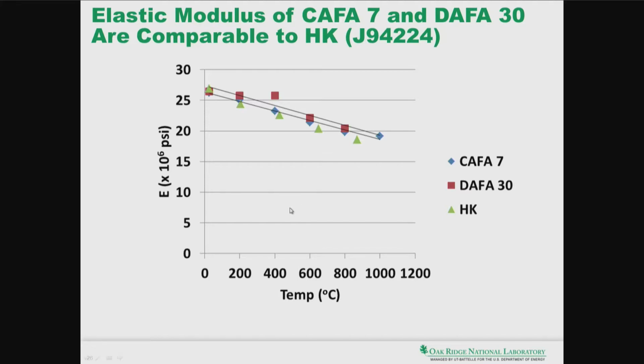And in the following, I'm just going to quickly run through some of the mechanical property data we have. What I'm showing you here is the elastic modulus as a function of temperature for these two alloys, CAFA 7 and DAFA 30. And you can see that the HK alloy is slightly lower in modulus, and if you're familiar with the data book, the HN and the HP are even much lower than these alloys. So if you are targeting applications that would traditionally use HK, this would be a good drop-in substitute for some of these alloys, but with the advantage of improved oxidation resistance.